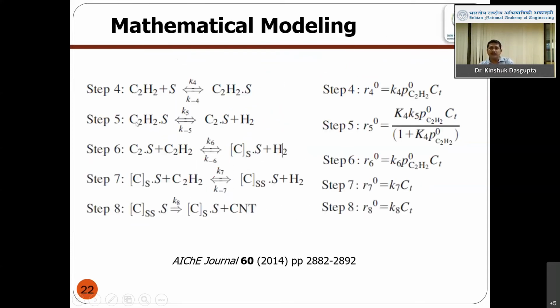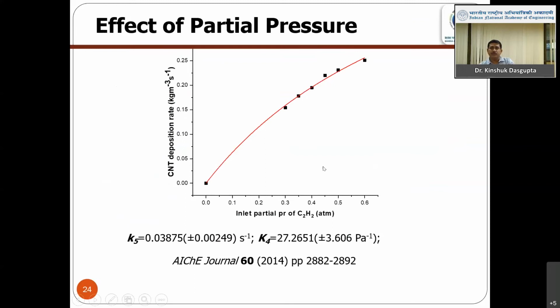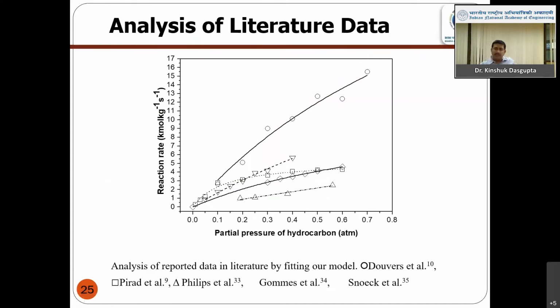That means the dissociation of adsorbed acetylene into carbon is the rate controlling step for carbon nanotube production in fluidized bed synthesis of carbon nanotube. So we could find the different rate constants, and we published this in the AIChE journal. We also took the published data of other authors and tried to fit it to our model, and we could show that yes, this model is universal, and we could really fit others' data into this model.